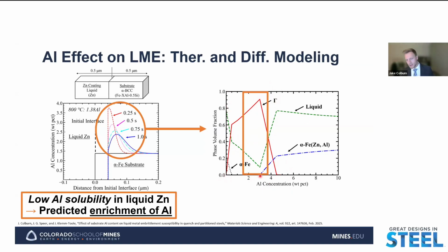So we see here that as we add aluminum up to about 3 weight percent aluminum, the liquid phase is destabilized and the gamma phase is further stabilized. But if we go higher than that, we then begin to stabilize the liquid phase and the alpha iron phase. But if we look at what our bulk composition is, starting at 1.38 weight percent and then potentially enriching in that 2 to 4 weight percent range, we're still in this orange box here of our composition where we have much higher equilibrium volume fractions of gamma phase stable as compared to the liquid phase.